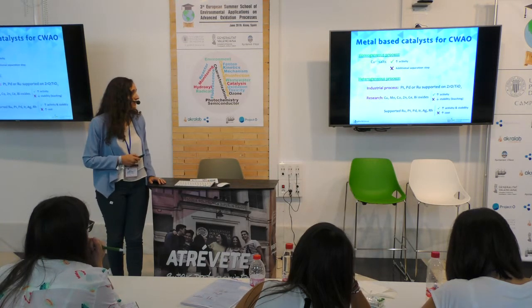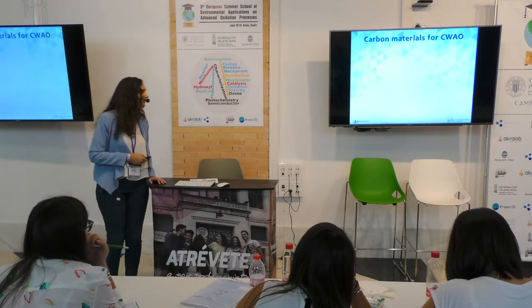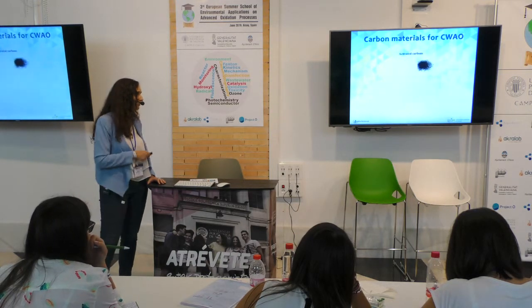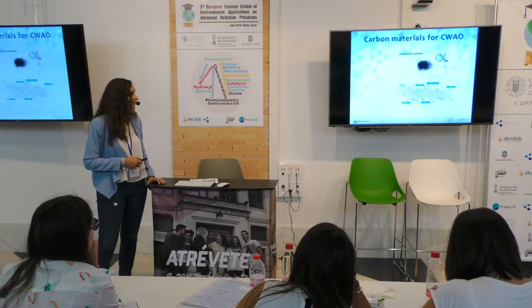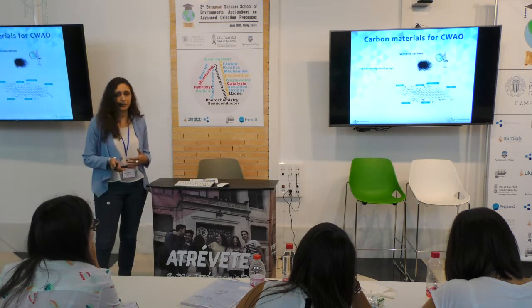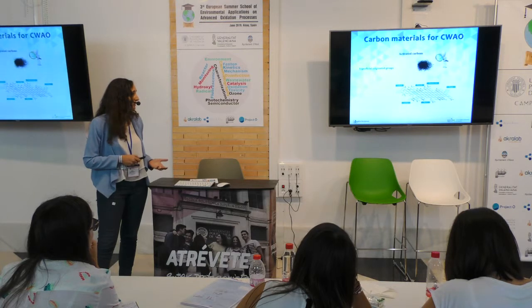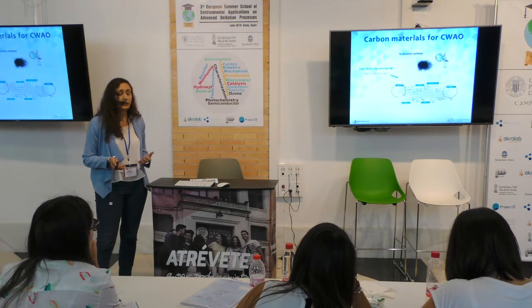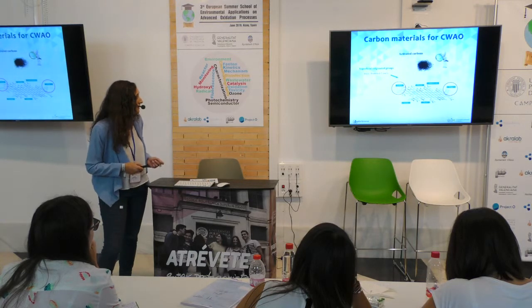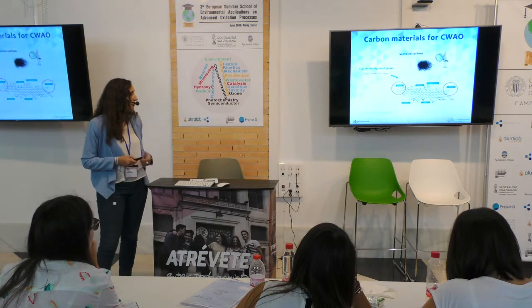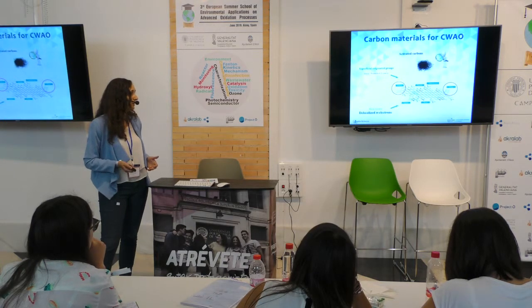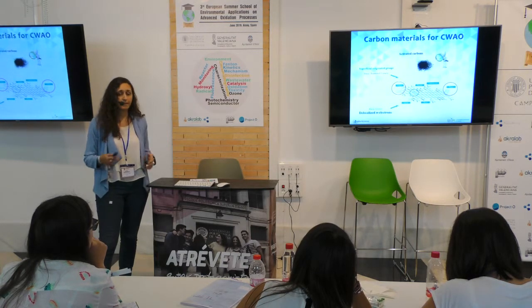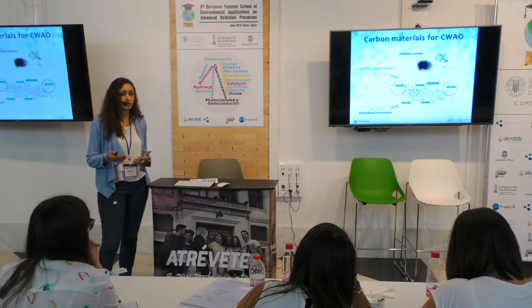Another alternative is the use of carbon materials. If we take a close look at the surface of activated carbons, we see different superficial oxygenated groups. Some of these groups can act as basic Brønsted sites, like chromenes and pyrones. We also have localized π-electrons that act as basic Lewis centers, which will be the electron donors for our process.